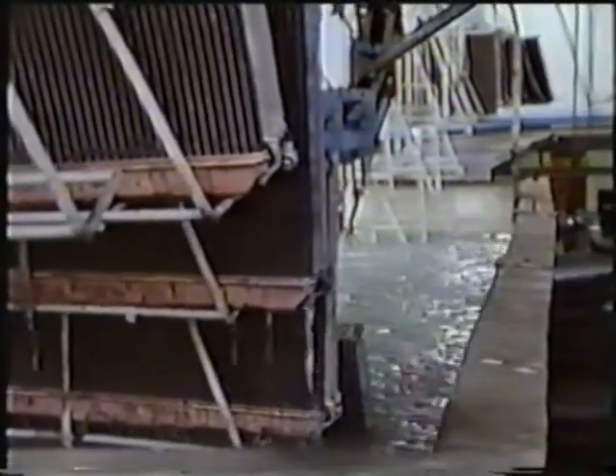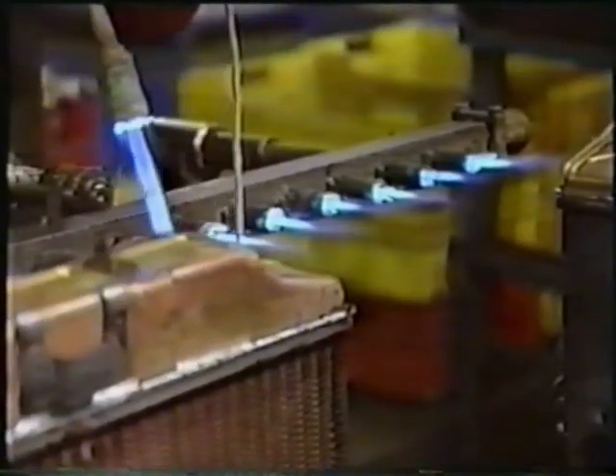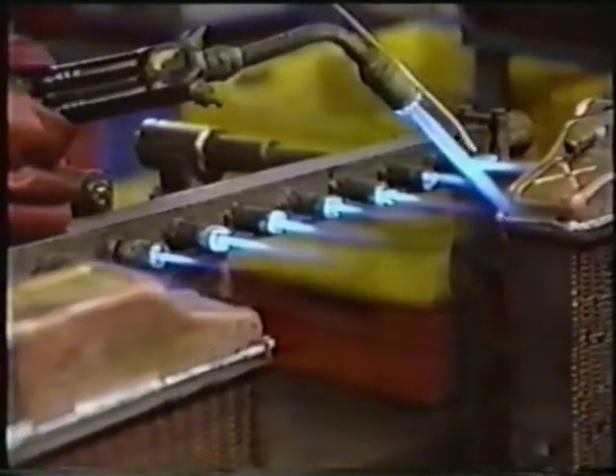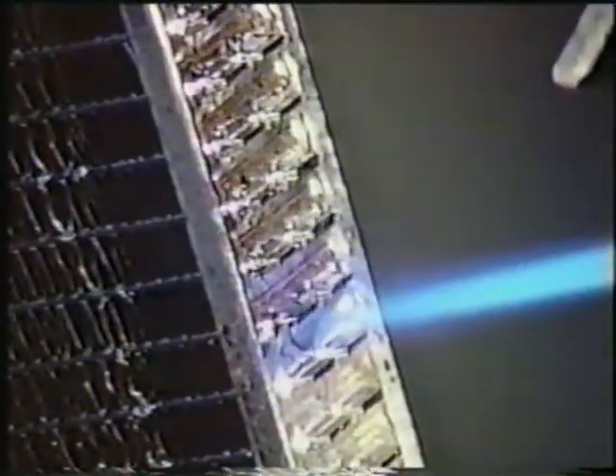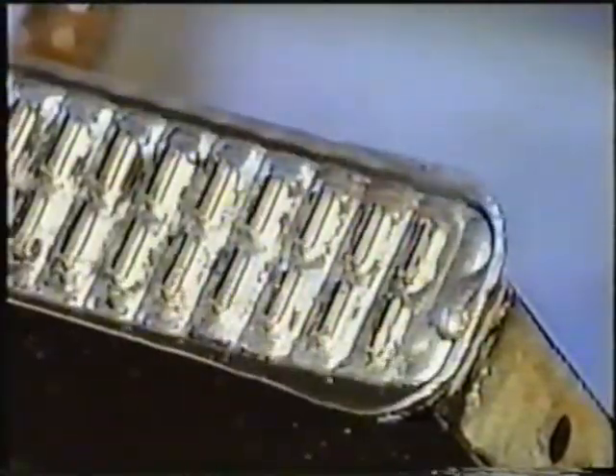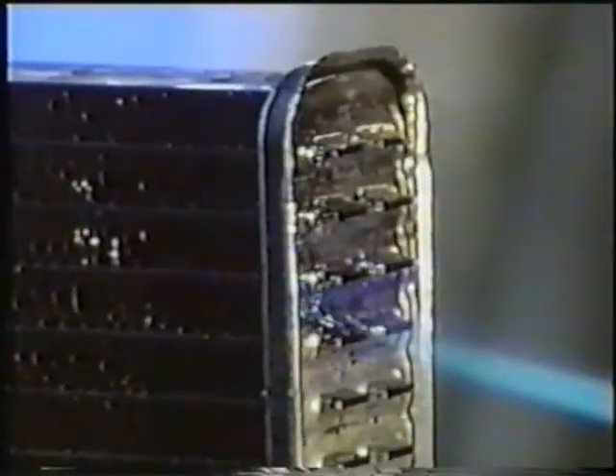Motor vehicle radiator manufacturers use solder with very low tin content, which means after 3 or 4 years in service, the solder on the radiator can lose its strength and a tube to header plate leak can occur. This may show up first at only one end of the core. It can be only the start. Tube to header plate leaks will soon start leaking at other places as well. So, unless a really low-cost job is requested, we should re-sweat all the tube to header plate joints.